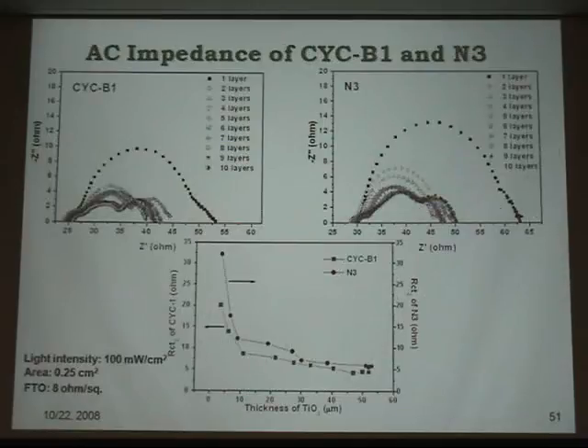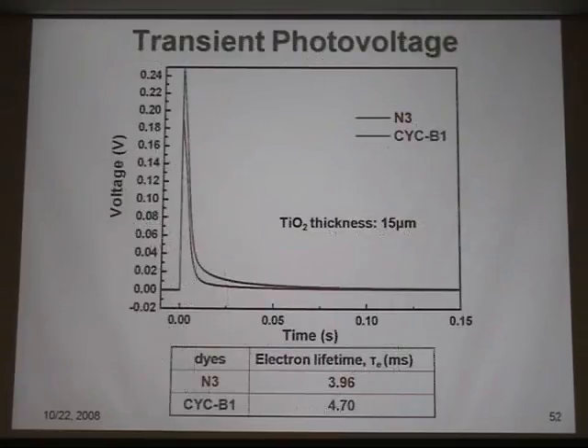Now, again, if you look at this AC impedance, you can easily find you need to have 4 coatings, 1, 2, 3, 4, to stabilize the efficiency, but for the resistance, you need only 2 coatings to get charge transfer resistance stabilized. So in terms of charge transfer resistance, our dye has some advantage over N3, showing lower resistance. Again, with photophysical measurement, our dye also has a longer lifetime.